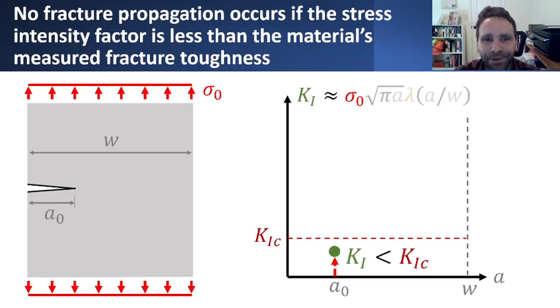Okay, in that particular scenario, we can come up with what is the stress intensity factor? We can go to those tables that we had previously and figure out what is the actual stress intensity factor expressed in terms of this far field stress state, sigma naught, in terms of other aspects of the geometry, like the initial crack length, A, and also including some other effects like the geometry dependent correction factor, or the relative crack size, A, divided by the relative width of the plate. So some lambda, let's say, the correction factor for the geometry, depending on A over W.